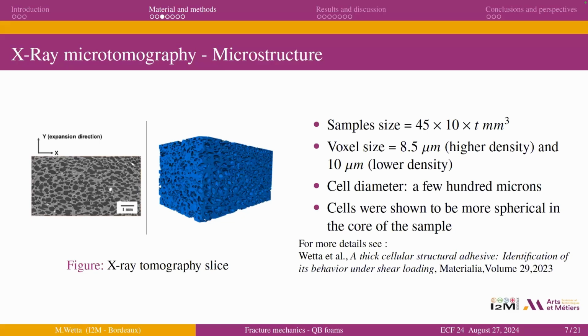In our case, we have a gradient of the microstructure in the thickness, and we have observed that cells were shown to be more spherical in the core of the structure. So we have some skin-core effect. But if you want more information about that, we have already published a paper on the link between the microstructure and the microscopic mechanical behavior.